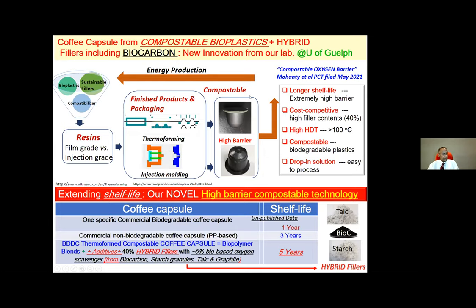So coffee capsule. I already gave some statistics on how much coffee capsule, the espresso type of coffee cup, is used. So we developed this with compostable bioplastic and with a hybrid filler, including biocarbon. Biocarbon, one of the fillers here, acted innovatively as an oxygen barrier in the whole composition. Specifically biocarbon surprisingly acts as an outstanding oxygen barrier filler. We use a hybrid filler. So the hybrid fillers might be a combination of biocarbon, talc, a mineral filler, and starch granules. So we take the help of four, including another called graphite. We use the hybrid fillers and incorporate them into the biodegradable plastics and develop this type of high barrier packaging.